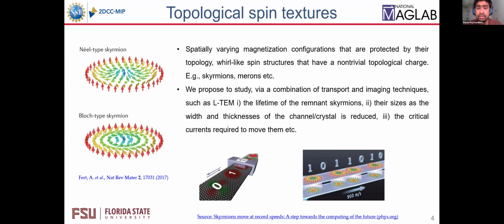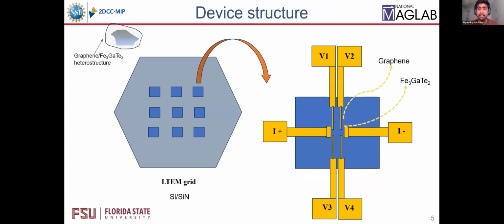So in this project, we propose to study with a combination of transport and imaging techniques, such as Lorentz transmission electron microscopy, can we get the lifetime of the skyrmions or their sizes and width as the thickness of the channel or crystal is reduced? Also, the critical current that is required to move the skyrmions within the channel. So that was the main motivation for this project. As you can see in this image, if we can manipulate the spin textures within the crystal, we can use this for various applications. So let me explain the device structure that we aim for.